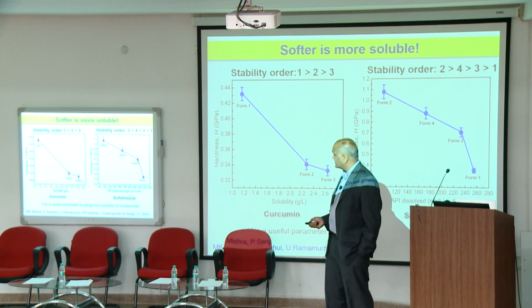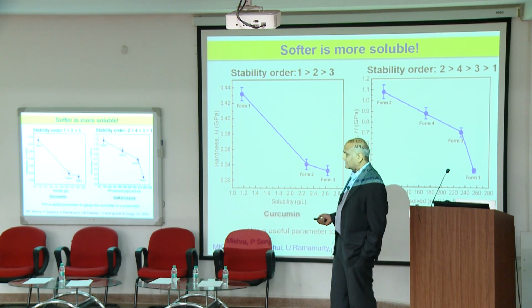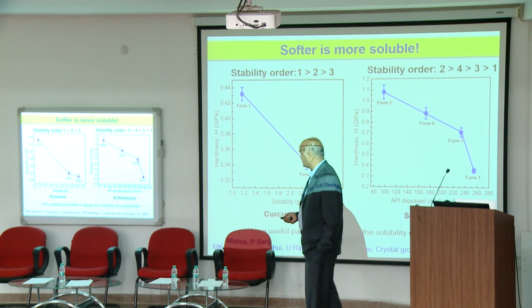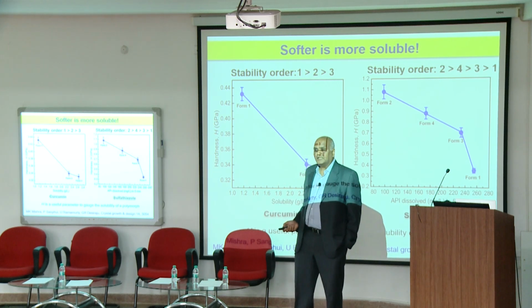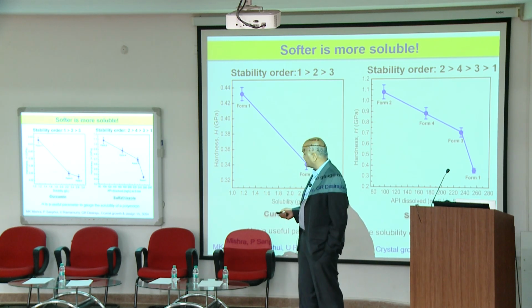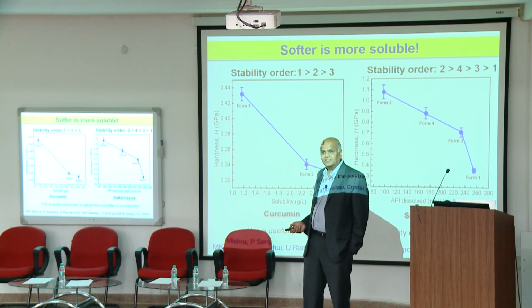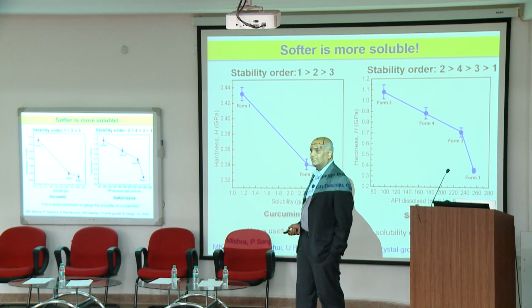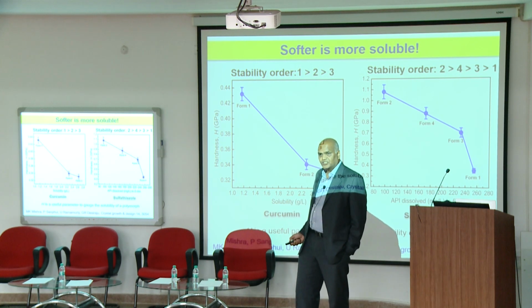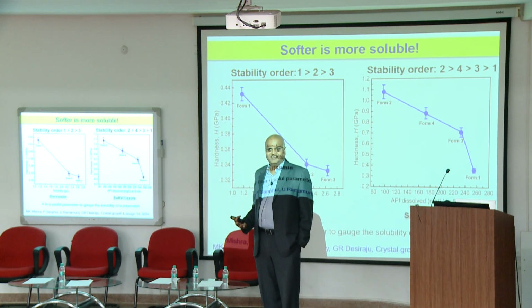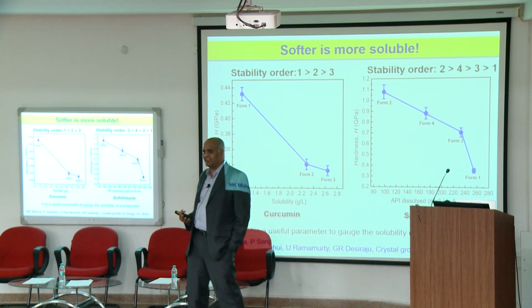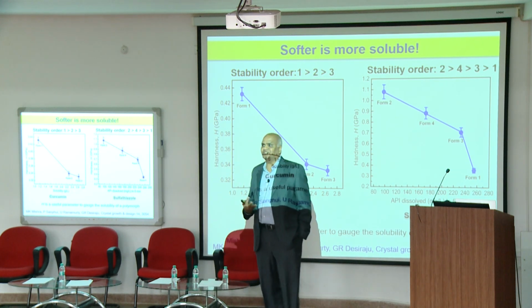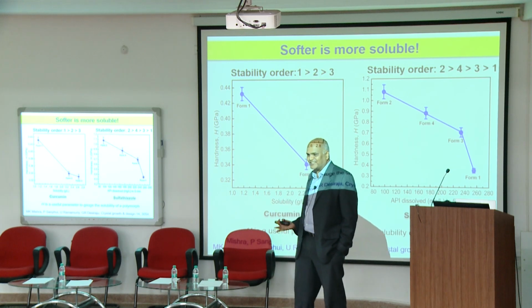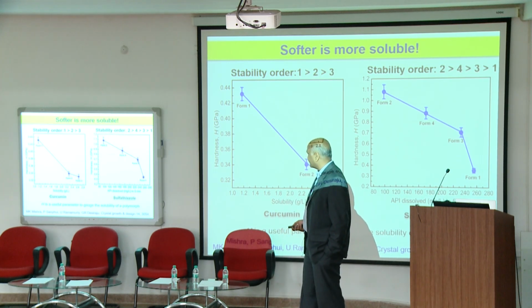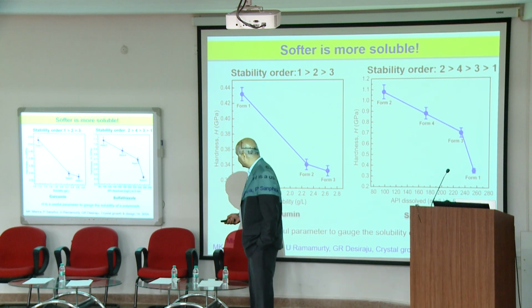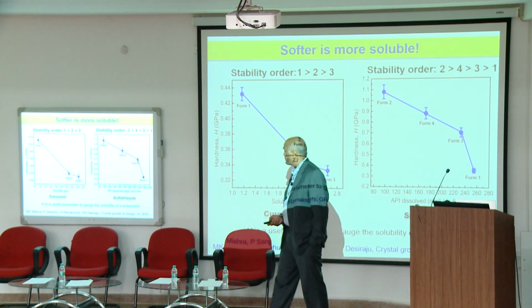order and what their solubility is. So hardness versus solubility, and you will see that the more stable it is, the higher the hardness, and the lower the solubility, because solubility is increasing. So the softer is more soluble. Maybe intuitively, I was arguing with my collaborator at that time, this intuitively makes sense to me, but scientifically these are correlations that you actually have to argue and say that this is the case.